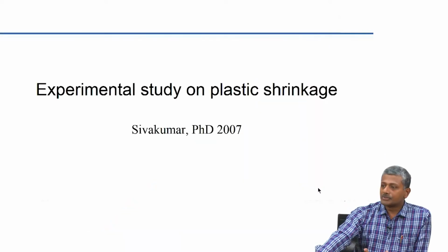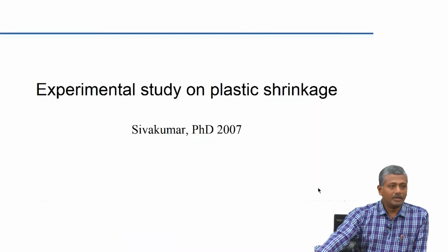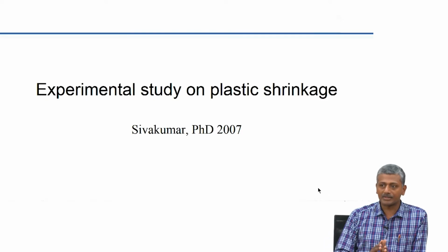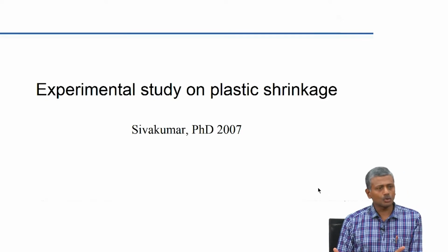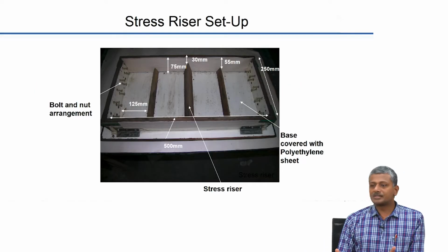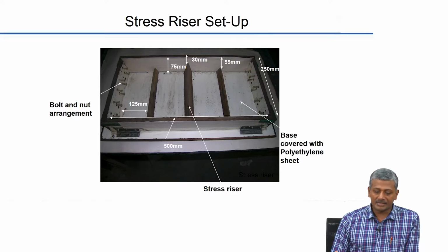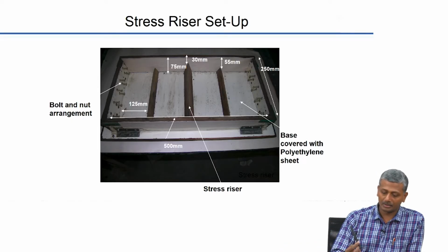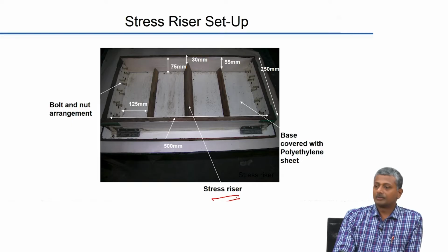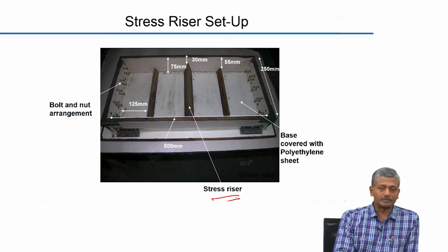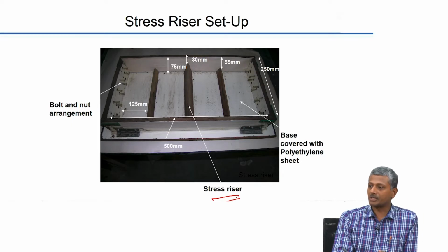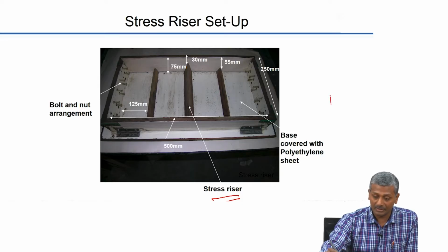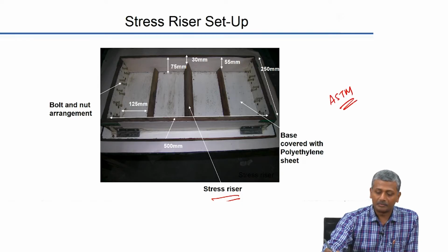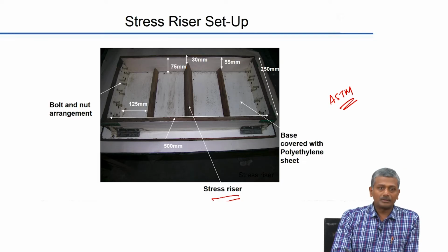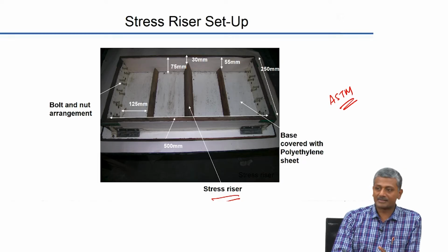Now, of course, to simulate a study in the lab involving a slab that is of very large dimension could be quite tough. So what is typically done is a stress riser experiment is usually conducted to determine the plastic shrinkage characteristics of concretes. And this experiment is now actually a standard ASTM standard. I am sorry that I do not recall the exact number. This standard talks about the use of this specially designed slab.